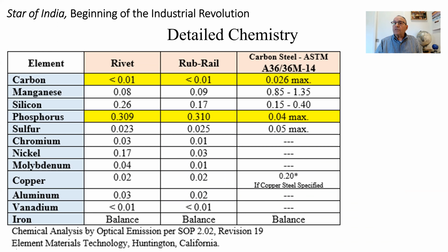One of the things that we know is that the open hearth process was very good at reducing the carbon, but it took a long time. But what it did not do is, aside from reducing the carbon, it didn't really affect the phosphorus or the sulfur much at all. Those didn't go away. They were still there in the open hearth processed low carbon steel. The Bessemer process, on the other hand, with this very volatile process, would drive out both the carbon and the phosphorus and the sulfur and also the silicon. It reduced the silicon quite a bit as well.